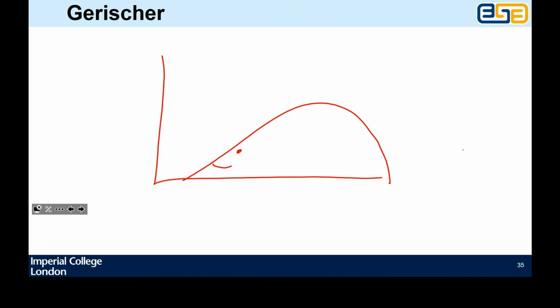It's definitely not going to look right, because your electrode is very likely to be 3-dimensional and have all kinds of varying properties as a function of space. It might be more porous near the top and less porous near the bottom. So it will end up being an interesting distortion of this and have all kinds of wobbles. But it might still be Gerischer physics that's governing it.